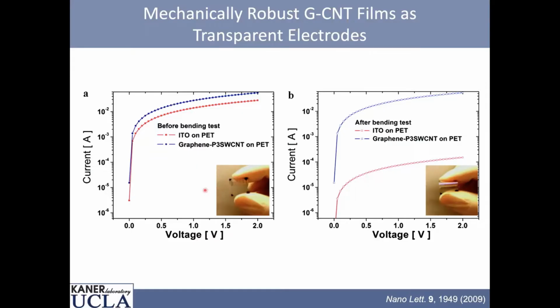So we just simply bent it 10 times back and forth. And of course, the indium tin oxide on plastic loses conductivity. It drops about 3 orders of magnitude. Why? As you bend it, you break up the crystalline domains. On the other hand, the graphene carbon nanotubes, you can bend all you want and nothing happens because they're molecular materials. So you can really think about using these things for transparent conducting electrodes.